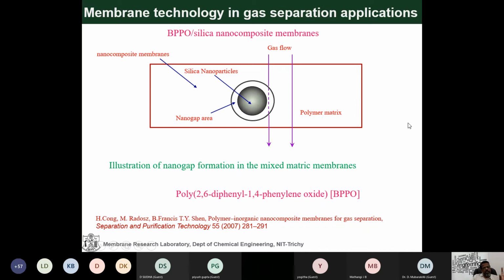Please carefully understand this slide, showing how gas is transported through the membrane. See the polymer matrix. This is the nano gap. These are silica nanoparticles. They create a nano gap between the polymer matrix and the inorganic materials, so there are many chances for gas to flow through the membranes, whether multi-gas or single gas flow. The gas flow depends purely on the hydrodynamic diameter of the gas.